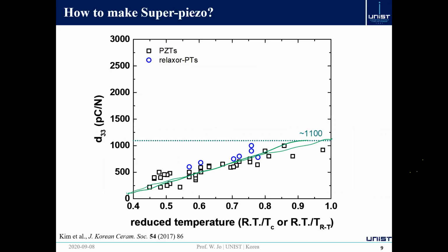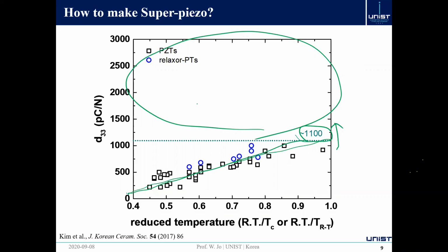That means if you bring the Curie point or depolarization temperature very near to room temperature, the maximum D33 expected from these polycrystalline ceramics would be somewhere around 1100 picocoulomb per Newton. So you cannot really go above this 1100 picocoulomb per Newton. Maybe, but this is just an empirical prediction. Some might go even above this value with a slightly higher Curie point, but at least this gives us a kind of direction of where we are heading. So 1100. But we have a huge empty space up there. How do you achieve this? How do we get a material with such a high piezoelectric coefficient?